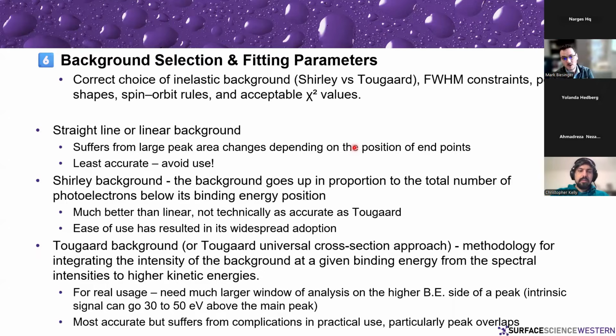The Tougaard background, or Tougaard universal cross-section approach, is a methodology for integrating the intensity of the background at a given binding energy from the spectral intensities to higher kinetic energies. It is very accurate in modeling what's going on in the inelastic, all the loss structure and the inelastic backgrounds. For real usage, to really take advantage of its accuracy, you need to use a much larger window of analysis on the higher binding energy side of the peak. Instead of that standard window that pops up on most instruments, you need to go much higher to really take advantage of all that intrinsic signal that's present. So 30 to 50 eV above the main peak.